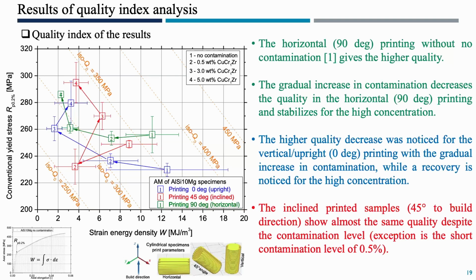What is challenging and needs to be figured out is the 45 degrees, which seems to be less immune to the cross-contamination. For no contamination, this is the only exception; with low contamination you have a drop in the quality. But for higher contamination, you see that there is a steady quality of the material.